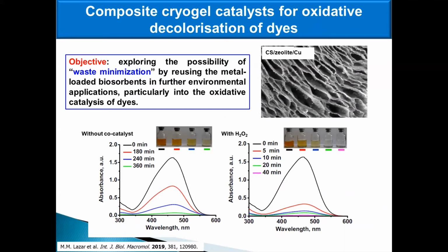In another study, we explored the possibility of waste minimization by reusing the metal-loaded biosorbents in other environmental applications, particularly in the oxidative catalysis of dyes. We investigated the methyl orange degradation by chitosan-based composites loaded with copper ions, either under ambient light or in a photo-Fenton catalytic system. As can be observed from the residual absorbance values, the decolorization of methyl orange solution was remarkably accelerated by the addition of hydrogen peroxide. Thus, the maximum absorption band at 464 nanometers drastically decreased in time and almost disappeared after 40 minutes of reaction.